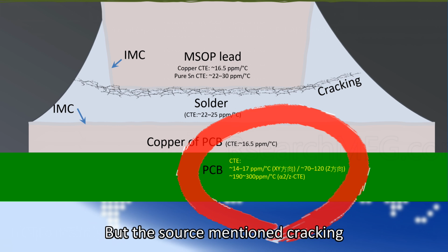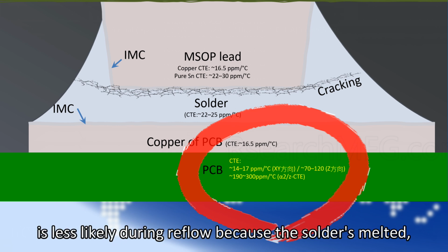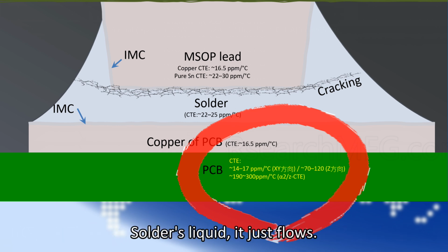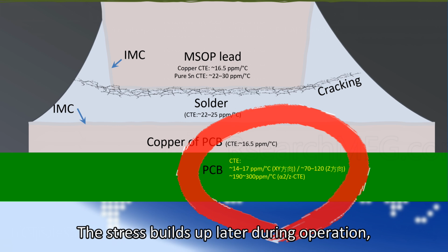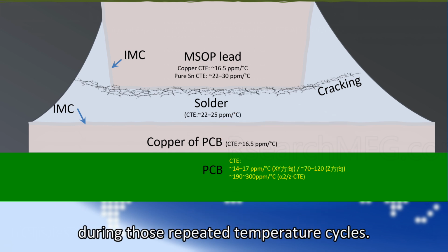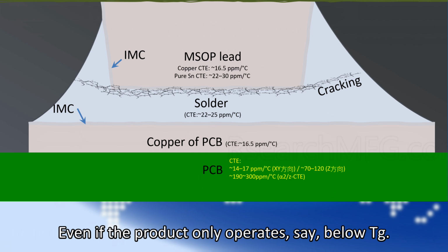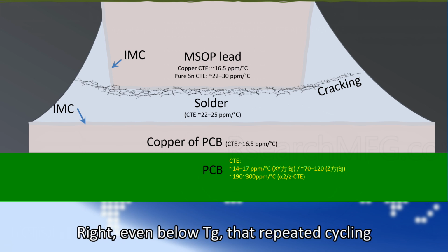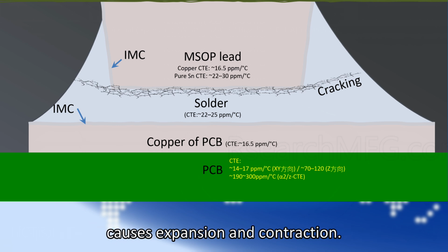Jeez. But the source mentioned cracking is less likely during reflow because the solder's melted, right? Correct. Solder's liquid, it just flows. The stress builds up later during operation, during those repeated temperature cycles. So even if the product only operates, say, below Tg? Right, even below Tg, that repeated cycling causes expansion and contraction.